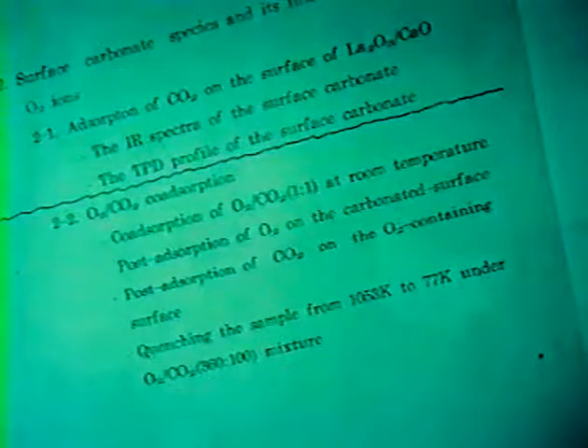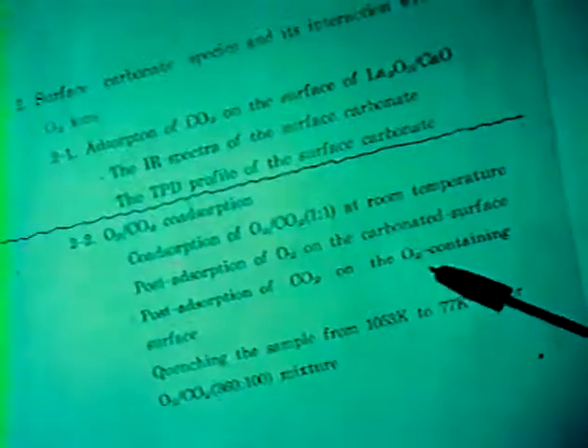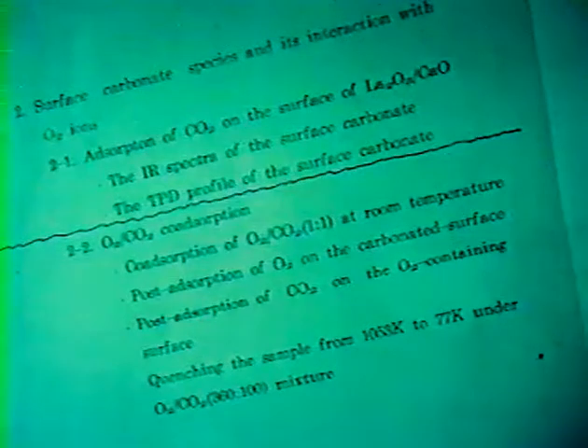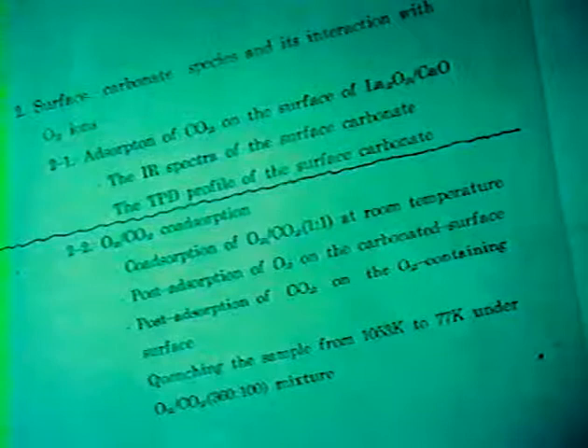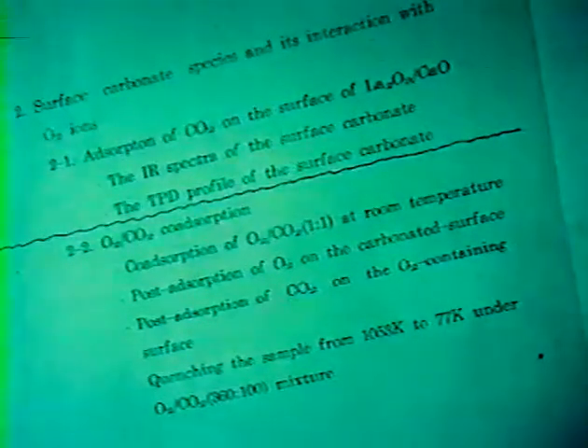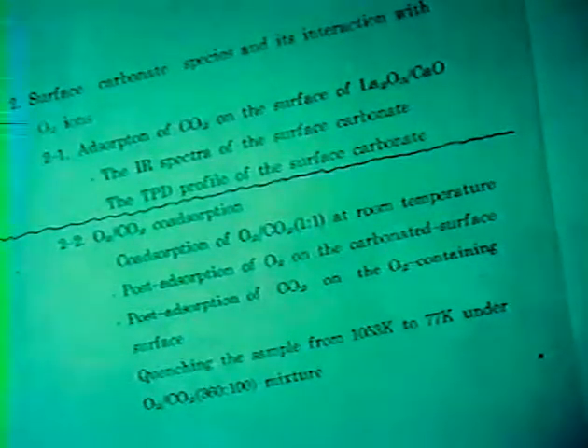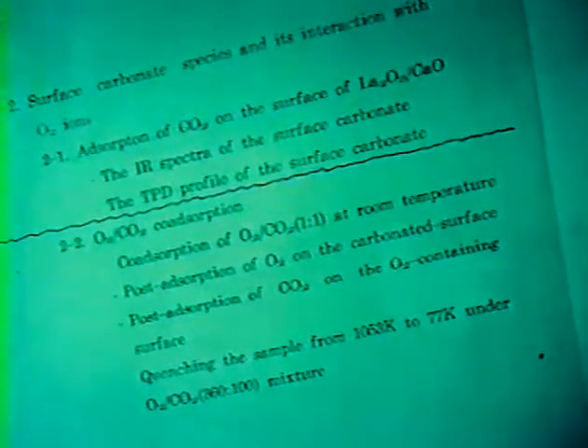If carbon dioxide was introduced on the superoxide ion containing surface, this led to an increase of the EPR signal of superoxide by a factor of 3. If the sample was quenched in the mixture of oxygen and carbon dioxide, no EPR signal of superoxide was observed.